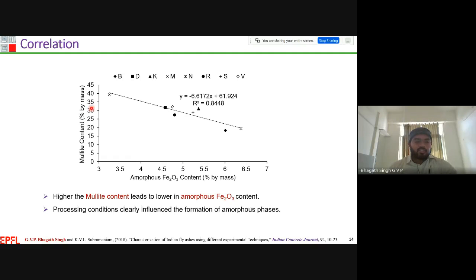And here the y-axis represents the mullite content, which is a crystalline form, and the x-axis represents the amorphous content. As you can see here, in all the fly ashes I have plotted, comparing source to source, the higher the mullite content in the fly ash, the lower the amorphous content. It means that the formation and the processing conditions clearly influence the amorphous content in our system, especially the mullite phase.